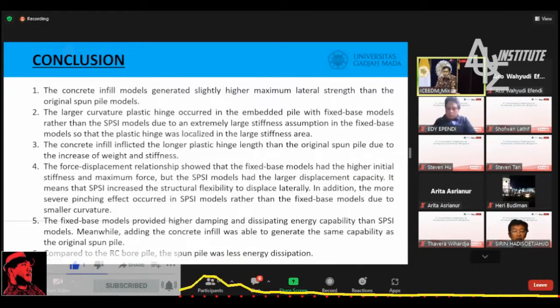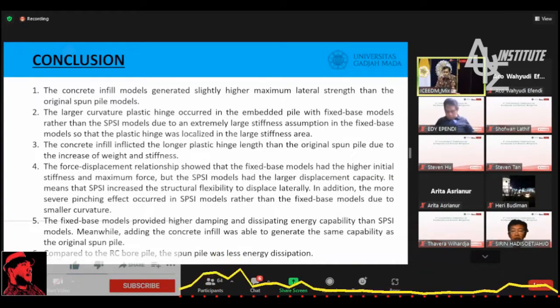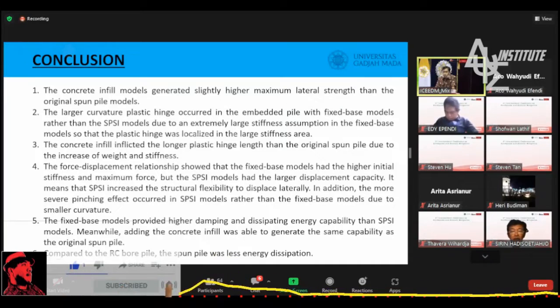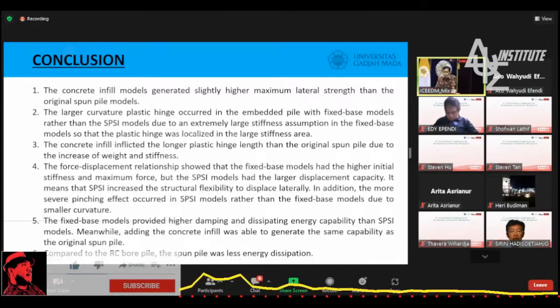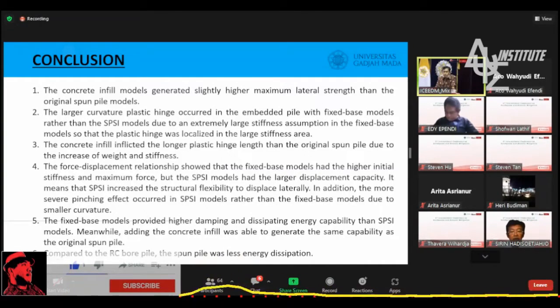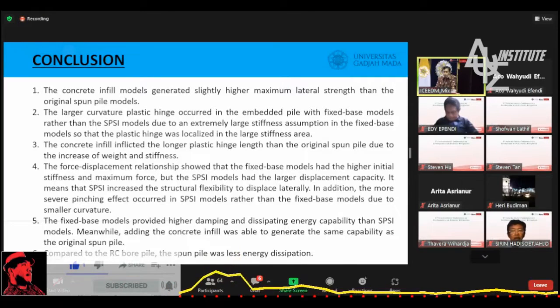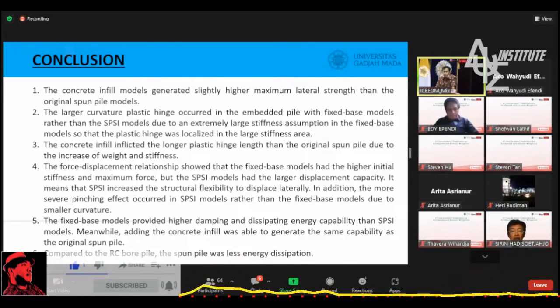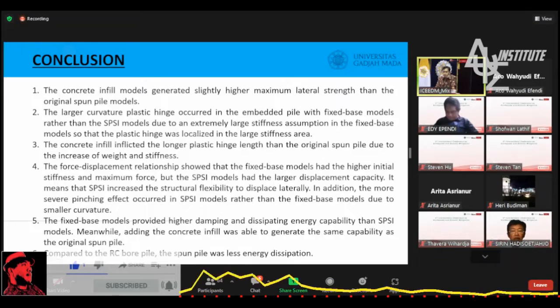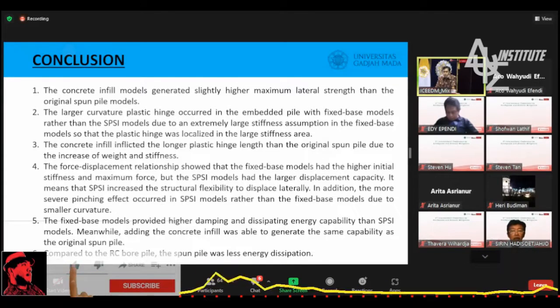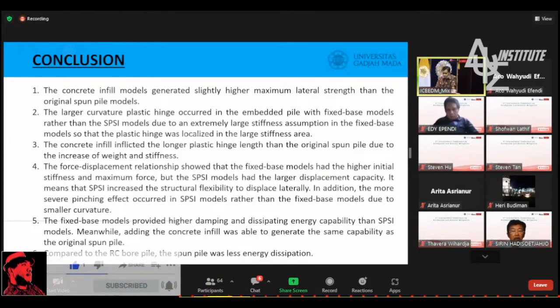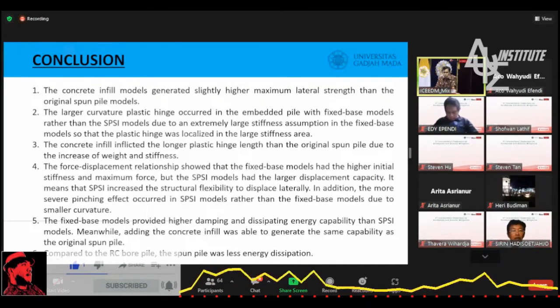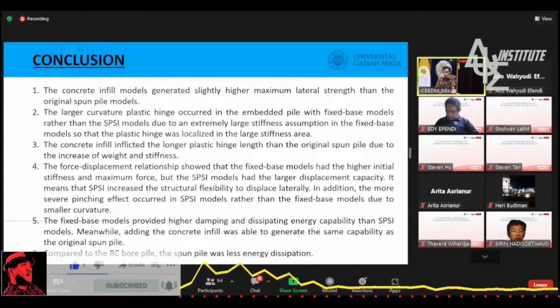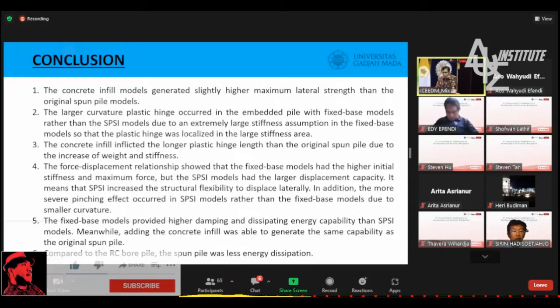In addition, the more severe pinching effect occurs in SPSI models rather than the fixed base model due to the smaller curvature. The fixed base model provides a higher damping and energy dissipating capability than SPSI in the large displacement. Meanwhile, adding the concrete infill was able to generate the same capability as the original spun pile. Compared to the RC pile, the spun pile had less energy dissipation.